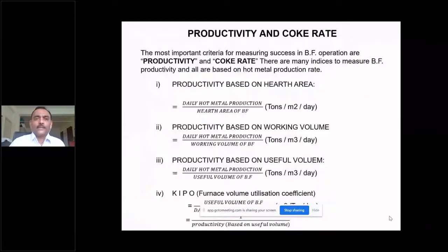So these are the definitions of productivity. It means from a furnace, if I am able to produce more tons, my productivity improves. As well as in case of coke rate. Coke rate is what? For producing 1 ton of hot metal, the amount of coke which is needed, that is called coke rate. In a fixed volume, we are charging two things. One is coke and another is non-coke. If I am able to reduce my coke, quite naturally, from that fixed volume, non-coke will incorporate more.